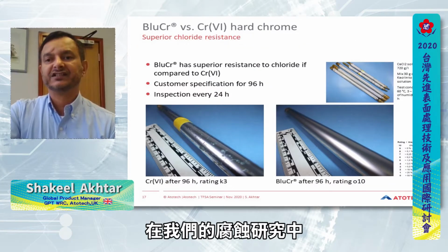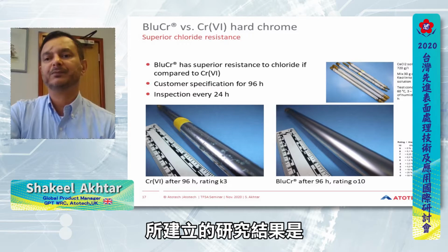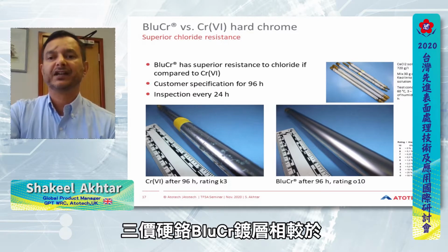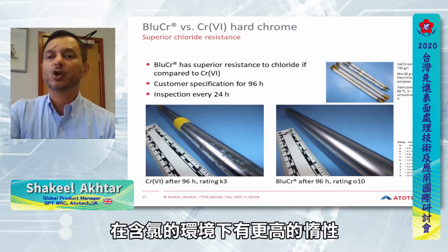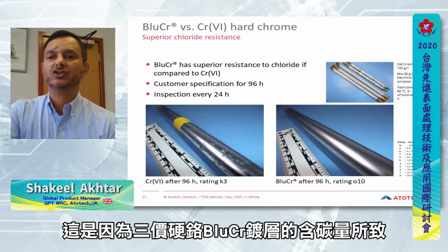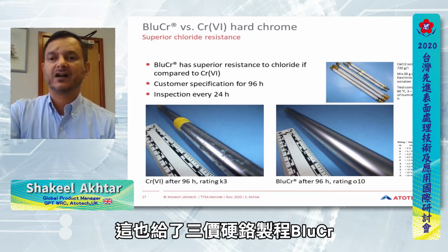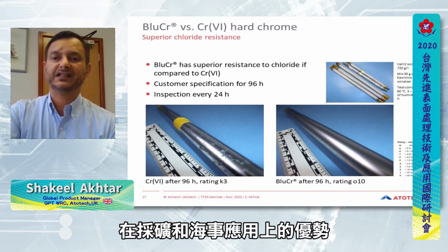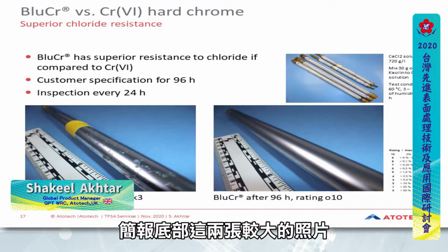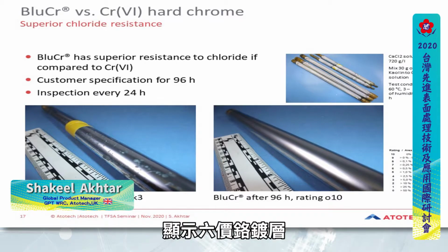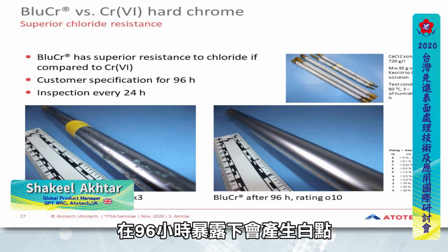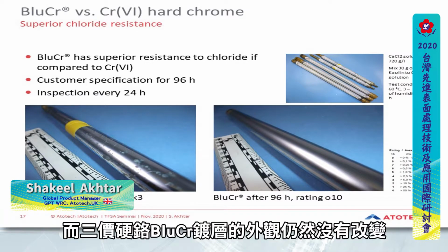During our corrosion studies, it was established that blue chrome deposit is more inert compared to the hexavalent deposit in chloride-containing environments due to the inclusion of carbon within the coating. This carbon gives the blue chrome an advantage in the mining and marine applications. The two bigger pictures at the bottom of the slide show that chrome 6 develops white spots after 96 hours of exposure, whereas the blue chrome remains unchanged.